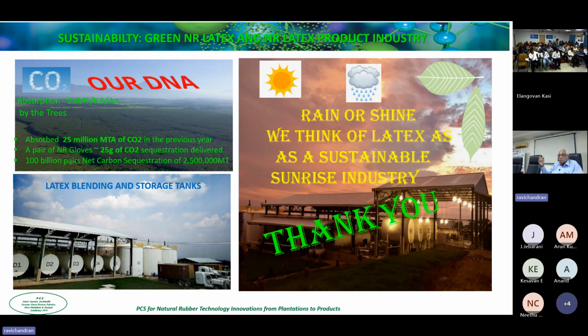we did recycling with gloves at Gujarat Reclaim, but we found that the rubber content was too high, so we had to add filler to make it more compatible for the user industry. Whereas with reclaim rubber, you get 50%, I think. Here you're getting 92% of rubber coming out. So it's very high and much higher molecular weight. Your strengths are higher. And in fact, the tire industry should try using recycled latex rubber rather than reclaimed rubber.